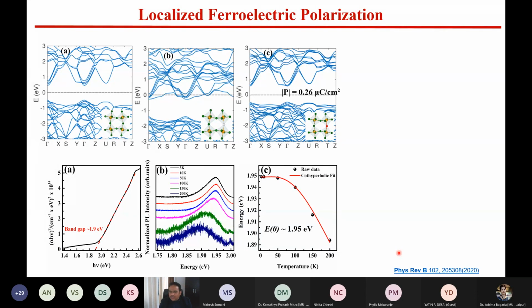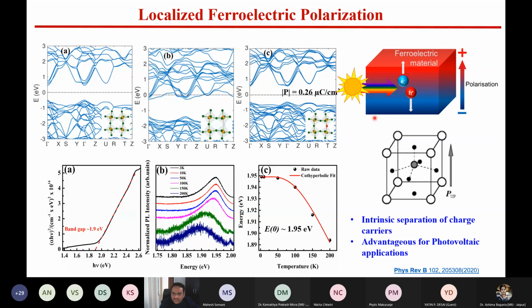Now this impurity oxygen will distort the structure as well as it will create a center of inversion symmetry breaking, and that will give rise to the polarization. And what we have estimated from our calculation is that the polarization is around 0.26 microcoulomb per centimeter square, which is very interesting for these materials. And that actually helps these materials to be a good photovoltaic material.